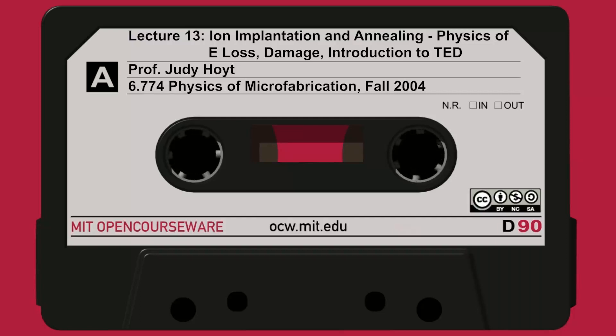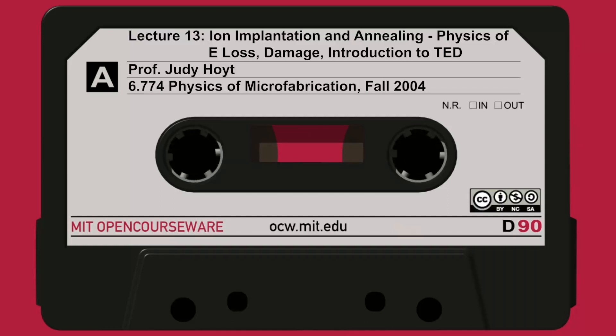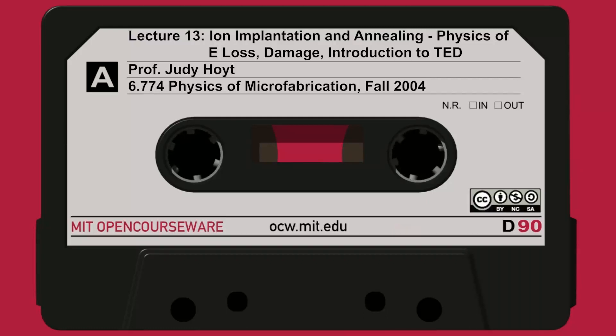On slide 17 — as we've talked about before, if you give it a high enough dose, enough of the crystal is displaced that it becomes completely amorphous, losing all of its crystal structure. There's no more long-range order. Once you've amorphized, there are no lattice sites — you can't knock somebody off a lattice site because there is no lattice site. This is a cross-sectional TEM — transmission electron micrograph — showing amorphous layer formation with increasing implant dose from left to right. This is 300 keV silicon being implanted into a silicon substrate.